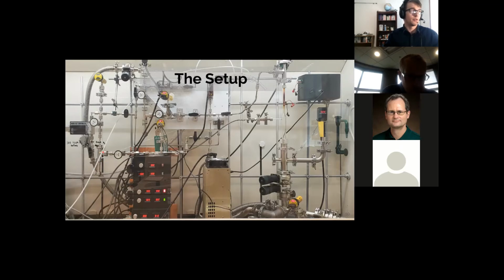And as the precursor gas flows through it, it carries the precursor downstream, meets with a couple other gases, which I'll talk about in a moment, carries them into the reactor where the nanocrystals are made, and down into a mesh where the nanocrystals are collected. The carrier gas we used is a mixture of 95% argon and 5% hydrogen.